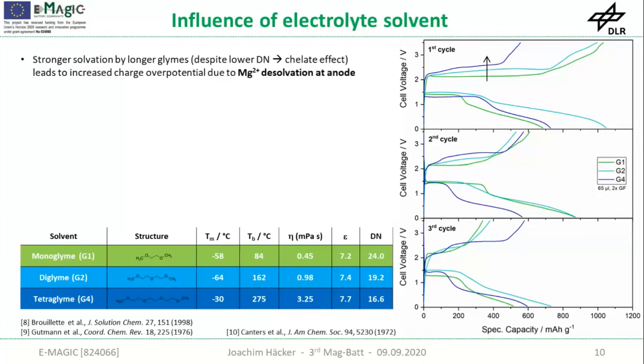If you have a look at the charge behavior, the overpotential rises with longer glyme length, which is due to increased solvation of the magnesium cation, despite the fact that tetraglyme exhibits a quite low donor number, or lower donor number than monoglyme, for example. But it's due to the chelate effect. So there's a strong solvation of the magnesium cations in this case, and this causes this overpotential, desolvation at the anode. And also the capacity gain is reduced during charge.